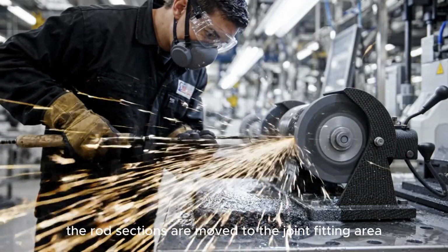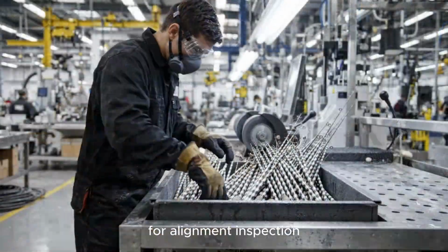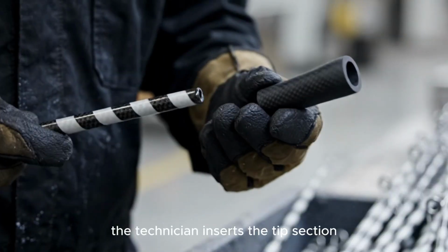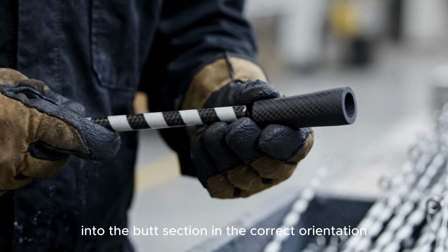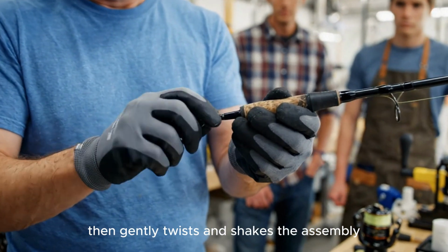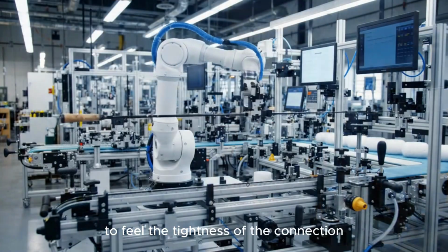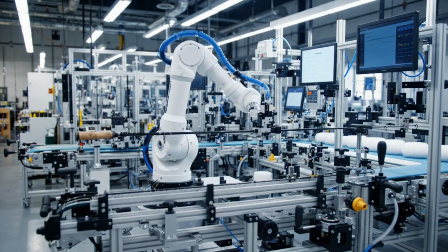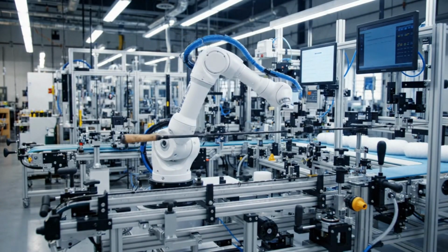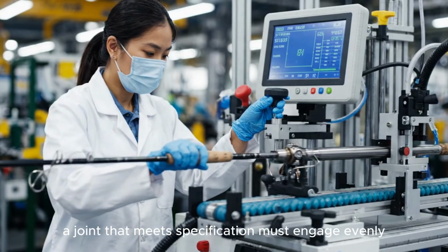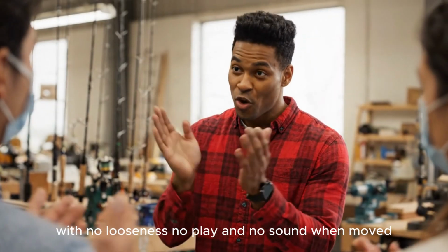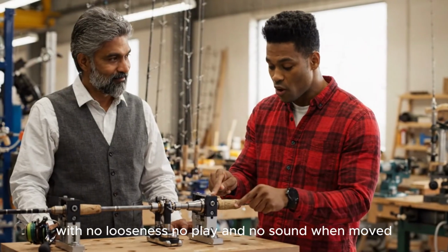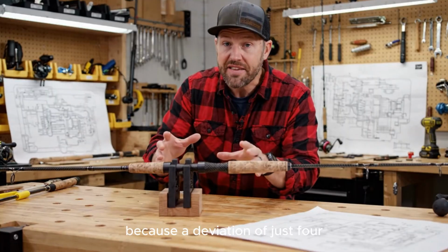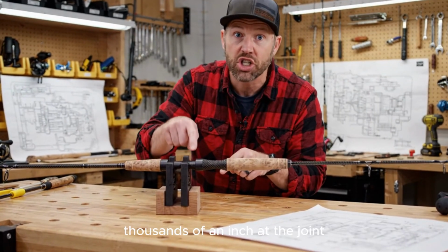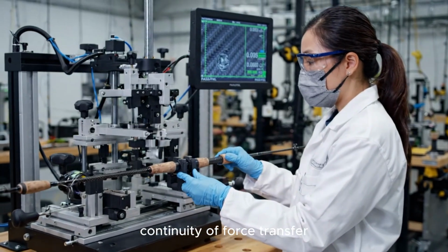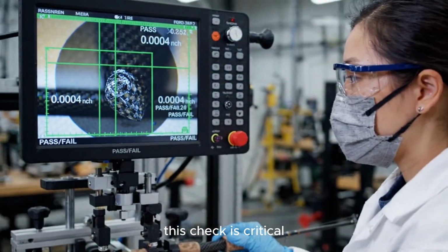After surface finishing, the rod sections are moved to the joint fitting area for alignment inspection. The technician inserts the tip section into the butt section in the correct orientation, then gently twists and shakes the assembly to feel the tightness of the connection. A joint that meets specification must engage evenly, with no looseness, no play, and no sound when moved. Because a deviation of just 0.0004 of an inch at the joint can completely disrupt the continuity of force transfer, this check is critical.